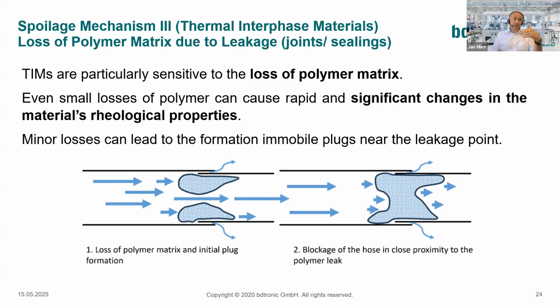First, you lose a little bit of polymer, which is presented on the left side of the picture, and this polymer transports through the joint, and the filler particles are too large and cannot pass that small cavity, resulting in the formation of such a plug which is in close proximity to the leakage area.